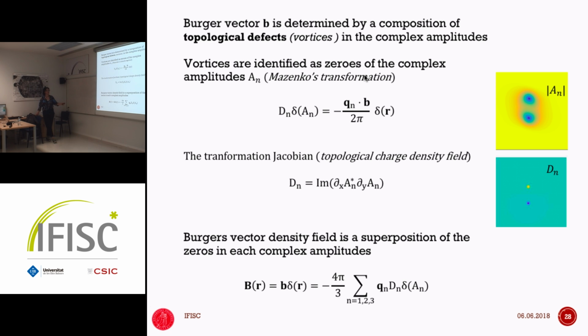And then this Dn is the Jacobian transformation matrix. So An is a complex variable, it has two functions, right? And r is a vector in the plane. So you have a 2x2 matrix, which becomes like this in 2 dimensions. Of course, it's a little bit more complicated if you have an order parameter in 3 dimensions, and the intrinsic order dimension of the order parameter is different. But even in that case, Mazenko has shown that you can still have a transformation from the defects to the zeros of the order parameter.